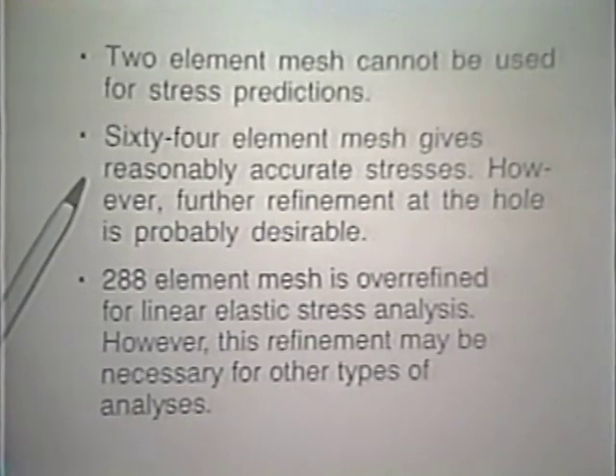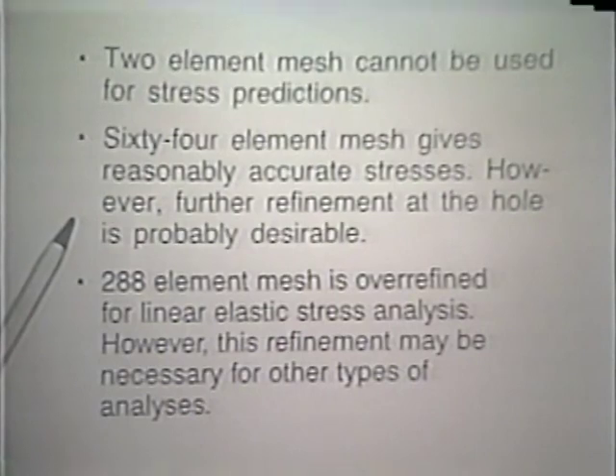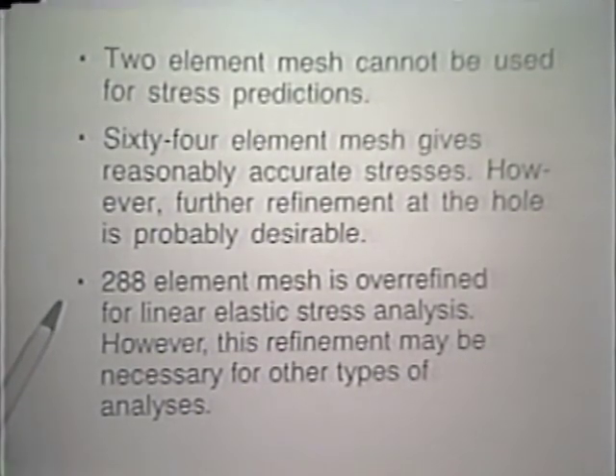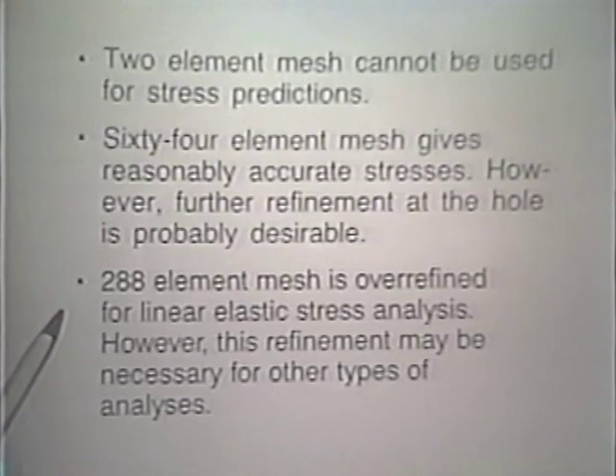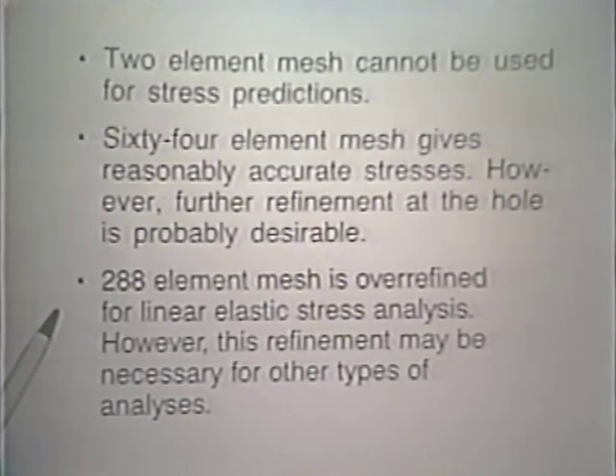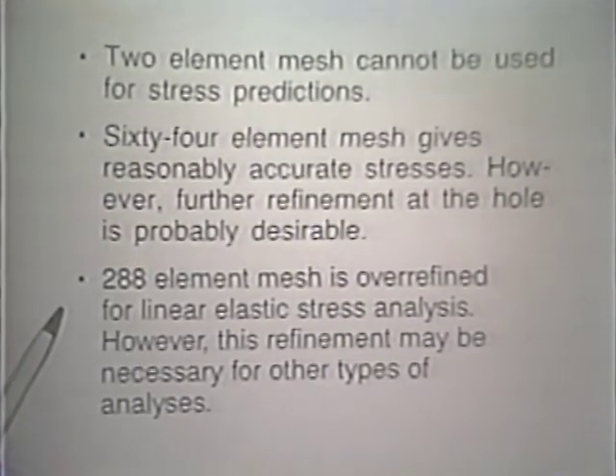So the 2-element mesh cannot be used for stress predictions is certainly a conclusion. It's not accurate enough. The 64-element mesh gives reasonable results for stresses and certainly very accurate results for the displacements. The 288-element mesh is probably over-refined for linear elastic stress analysis. However, for other types of analysis, for example, in elastoplastic analysis, if we want to have very accurate results, we might want to use actually this fineness of mesh.